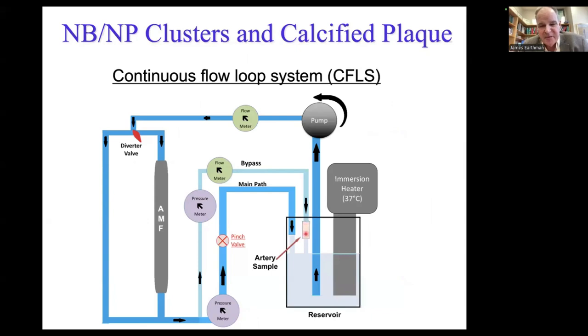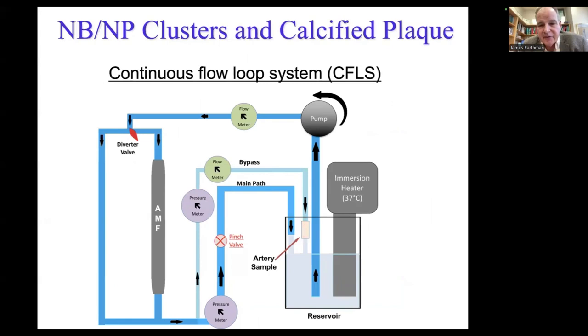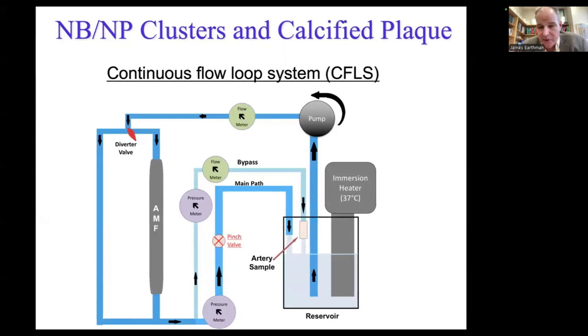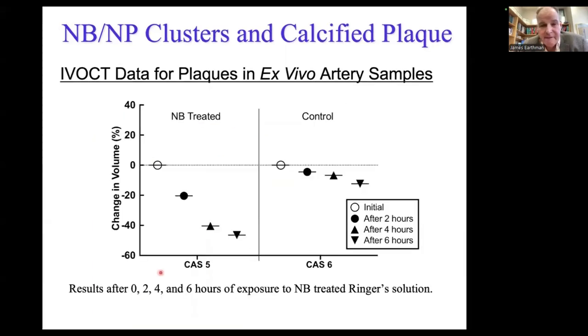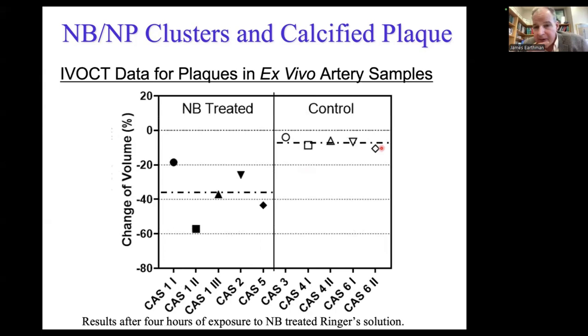through the artery, so it had the same approximate concentration of salt and other additives as blood, and also nanobubbles in some cases. And so we wanted to see if the nanobubbles could actually lead to greater dissolution of the plaque. And in fact, we did find that. This is after 2, 4, and 6 hours for one of the arteries that we were testing. And you can see quite a bit of change here in terms of the reduction in volume of that plaque. This was in a control artery, very similar. Again, we were using Ringer's solution without phosphate in it, so we did expect a little bit of reduction in the plaque in that solution, but it wasn't nearly as much as with the nanobubbles.